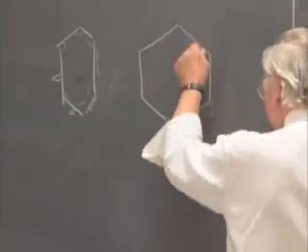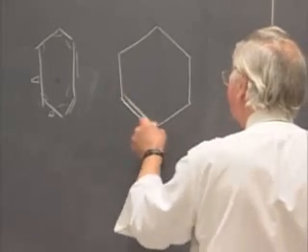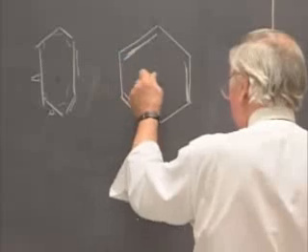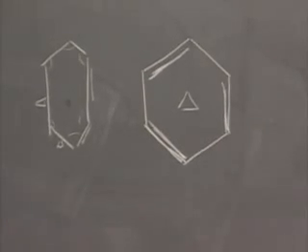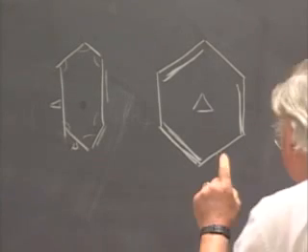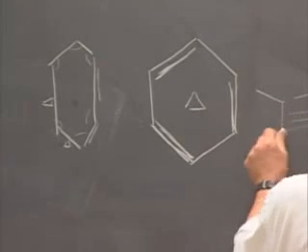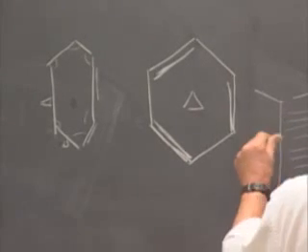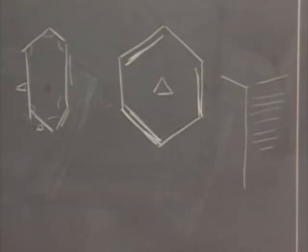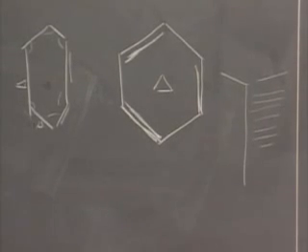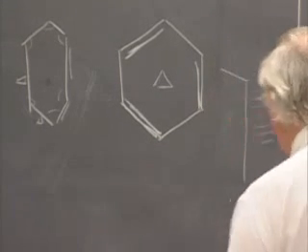Quartz has a hexagonal shape very often, but actually only this face and this face are symmetrically equivalent. There's only a threefold axis in there. And if you look very carefully at this crystal, you can see some difference there too. The neighboring faces very often have striations, very faint striations on one face, no striations on the neighboring face. So you find out all that you can, you have to make some assumptions, and then on that basis decide the symmetry. Let me give you another example.